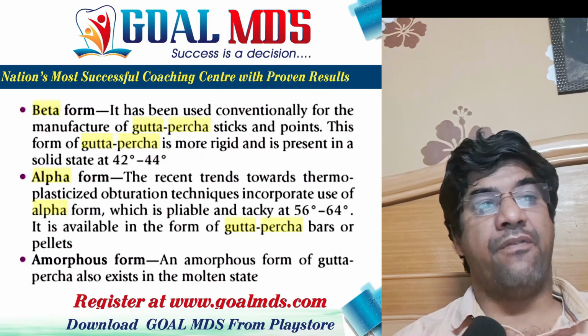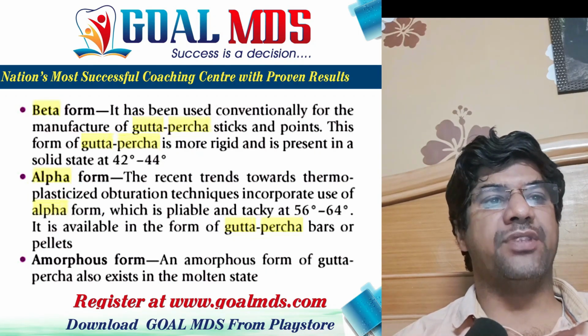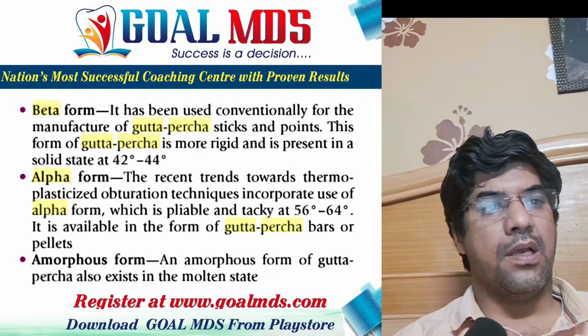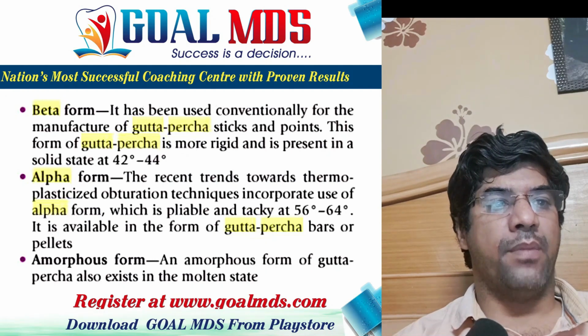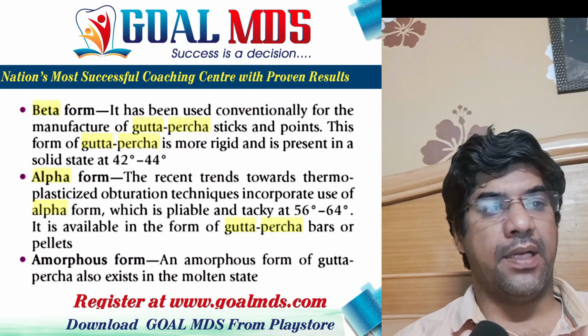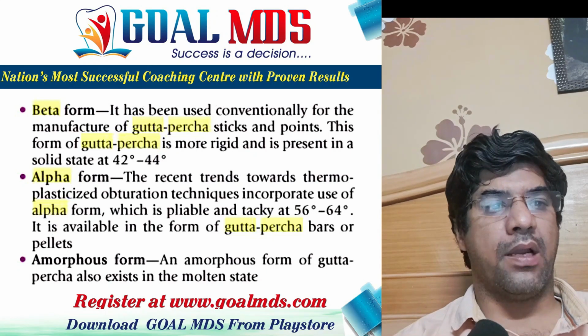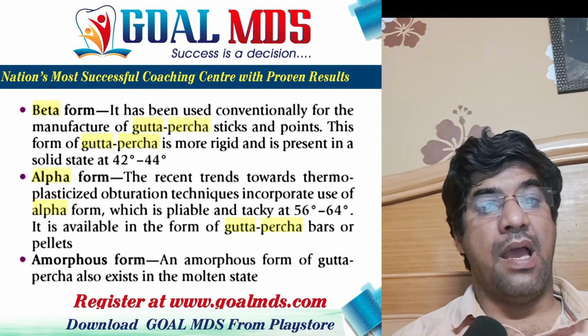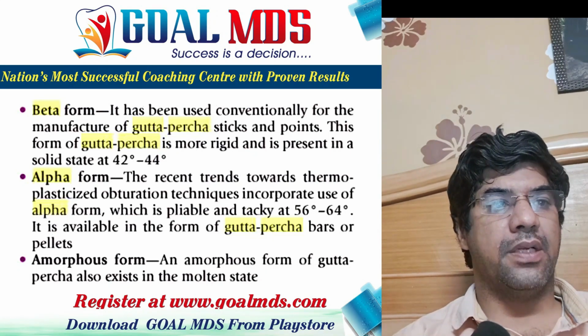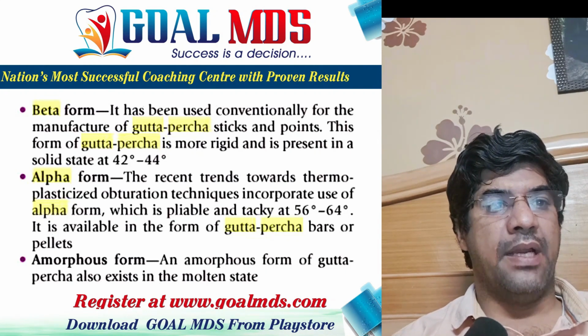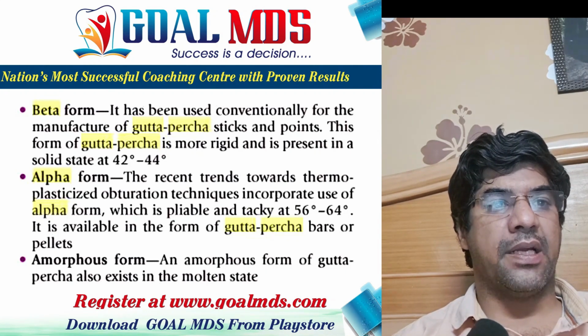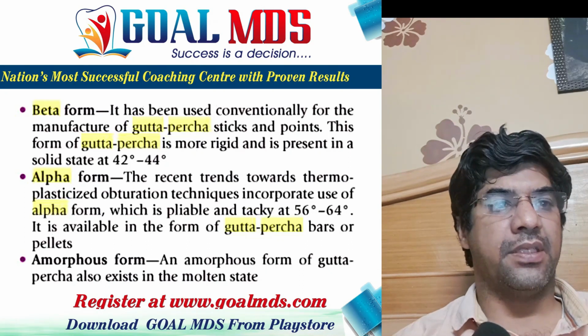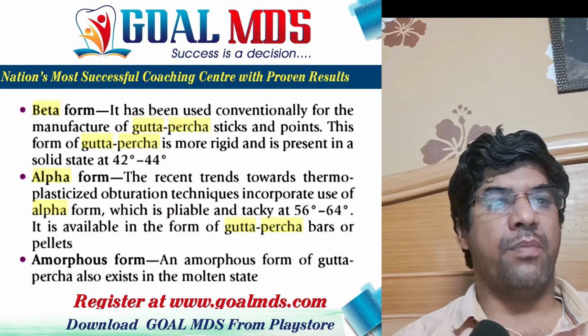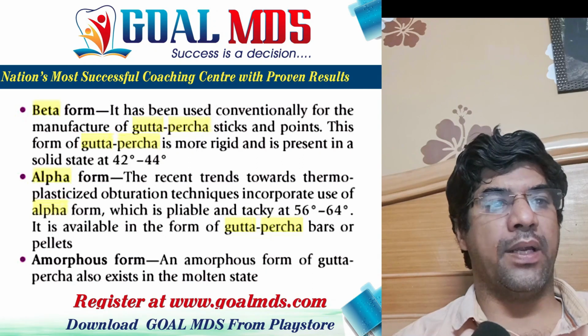It is the alpha form we use in the thermoplastic obturation technique. Whereas the beta form is rigid, solid, compactable, and elongated, with a higher viscosity. It is used for manufacturing Gutta Percha points and sticks. Whereas the amorphous form exists in the molten state.